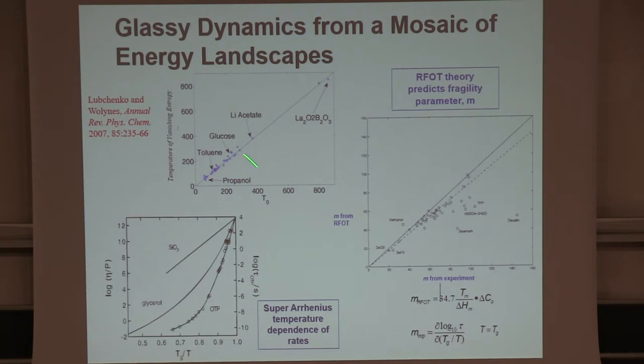One was, of course, the thing we've heard many times, that the temperature at which the configurational entropy should vanish should correlate with the temperature at which, in the Vogel-Fulcher law, the rate should go to zero. Well, here's 50 substances, not calculated by me, not culled from the literature, just taken by Austin Angell. Now, maybe he screwed around with things. But this is a thermodynamic measurement here. This is a kinetic measurement here. And you can see that the data fall very much on that line. That's not a fit. That's the line of slope one.